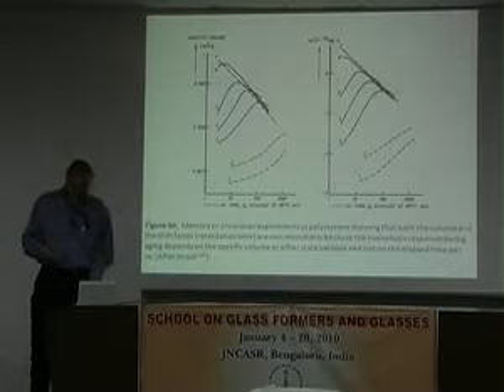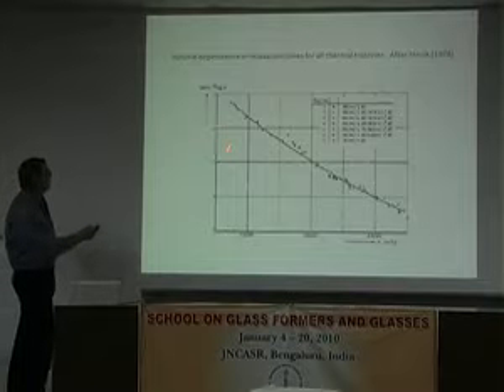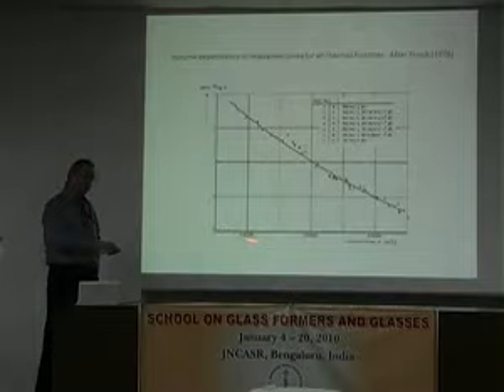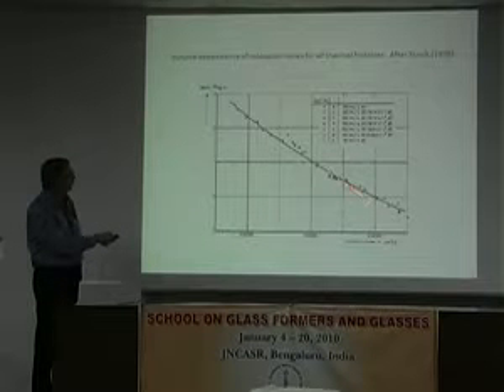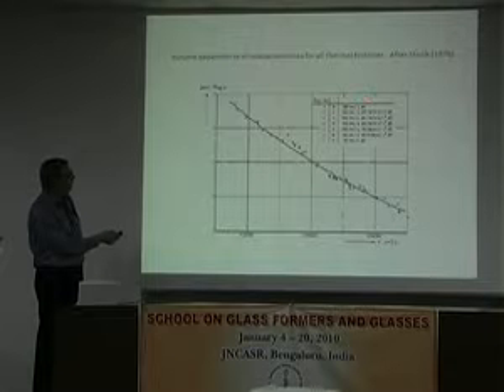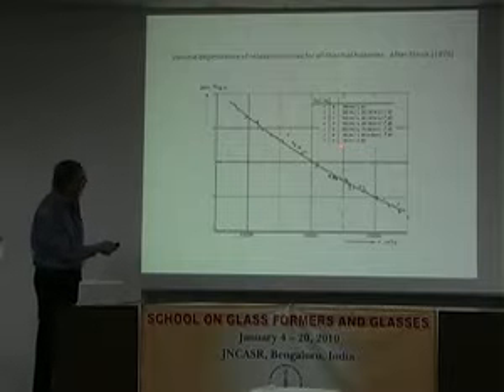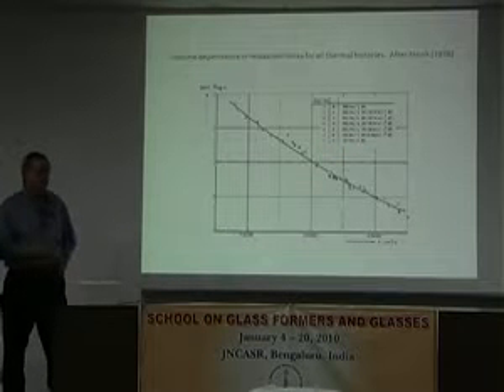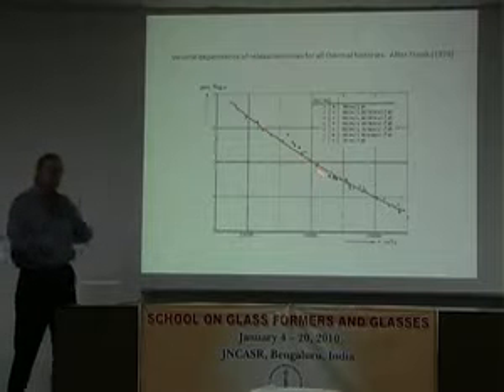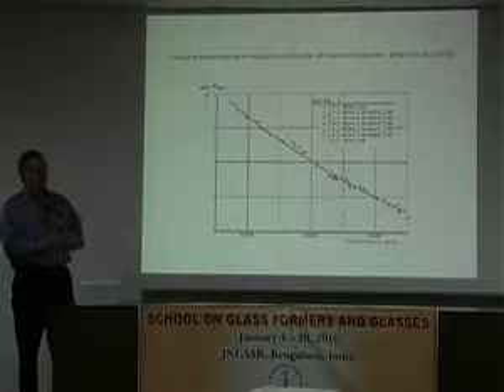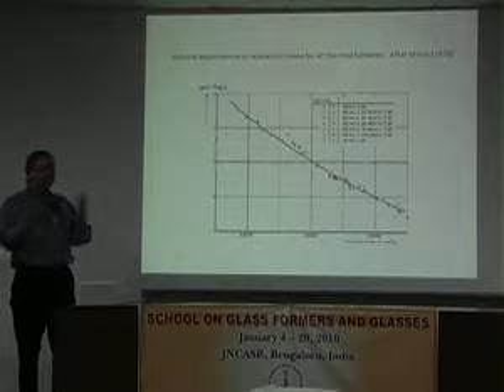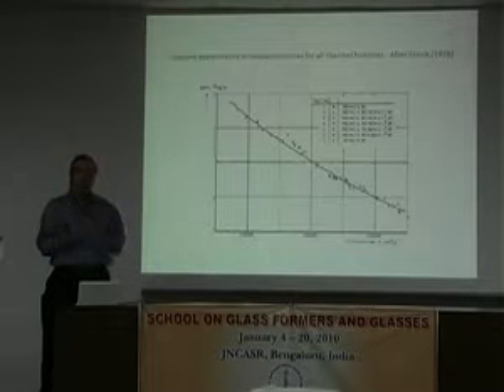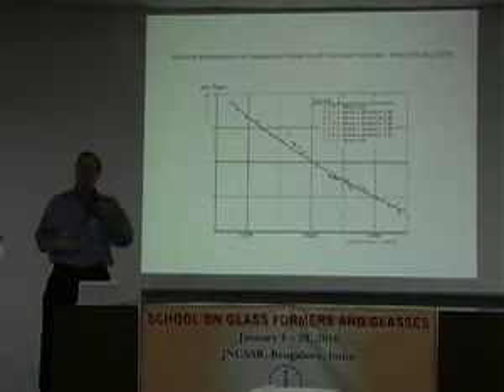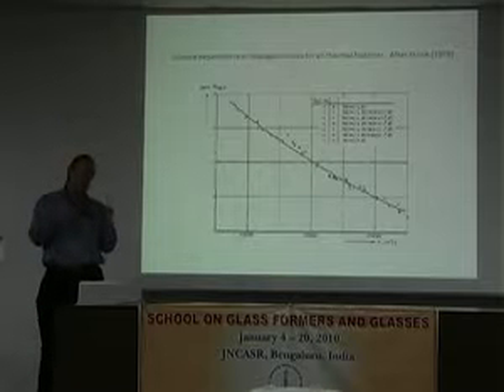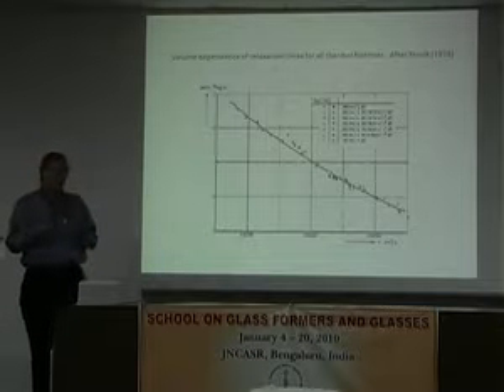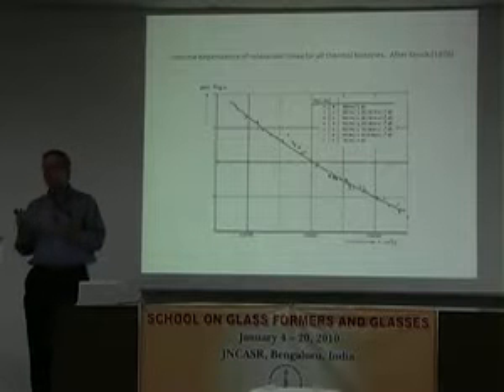So how about quantitatively? Struik did this whole series of experiments, and you see if we plot the log of these shift factors as a function of the specific volume, they fall pretty much on a single line for these down jumps and then up jumps. And here he doesn't show the asymmetry, but the asymmetry also falls into that category. So what we see is that the relaxation time depends on the departure from equilibrium, not on the elapsed time. And that's really important for structural glasses. And my comment is simply, it's a challenge for the colloidal community to come up with an equivalent ordering parameter for the structure so we understand what it means when you do a shear melting. Because in fact, the structural parameter might be something like concentration, or it might be some state of disorder which we don't understand yet, right? And so I think that's an important thing.